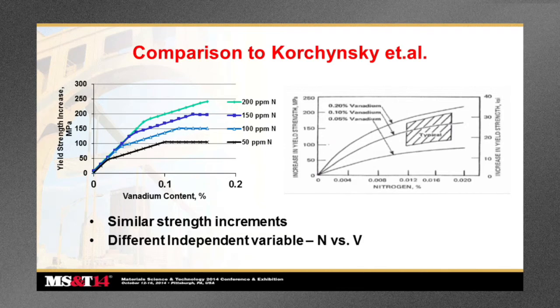Now looking at that literal model, as I called it, and comparing it to the Korchynsky model on the right, you can see at roughly the same axis of yield strength increase on the left, that in fact they're very similar. Of course, we have now put vanadium content on the lower axis rather than nitrogen content, which allows you to be predictive in how much vanadium you want to add, and we do that at various nitrogen levels to give you an idea where you need to be with nitrogen content when you're done. As you can see, the more vanadium added, the more nitrogen is needed to make maximum use of the vanadium that you have.